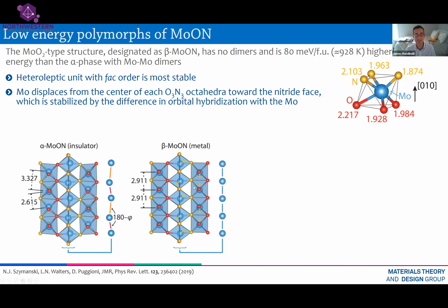Then there is a distortion that happens. So the structure is unstable in this phase. And the structure exhibits a dimerization where the cations, molybdenum, come closer together. And they form pairs, just like we saw in vanadium dioxide. So these two moly atoms get closer together, these two moly atoms get closer together, and then they also cant a little bit. This is a feature also seen in vanadium dioxide. And this material exhibits an electronic structure which is then insulating.